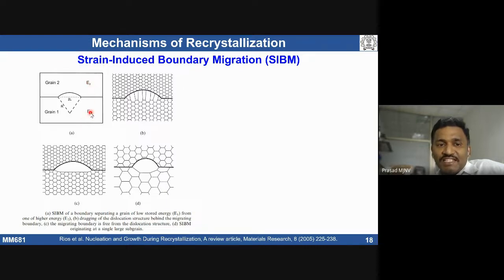At the same time, because of the difference in energy, the subgrains that form in grain 1 are different in size from the subgrains that can form in grain 2. Look here, it is schematically shown: the low energy grain has a relatively coarser subgrain, whereas the high energy grain has a relatively finer subgrain. At the interface between these two grains, the subgrain structure changes, and then becomes a fully strain free grain without any subgrains.